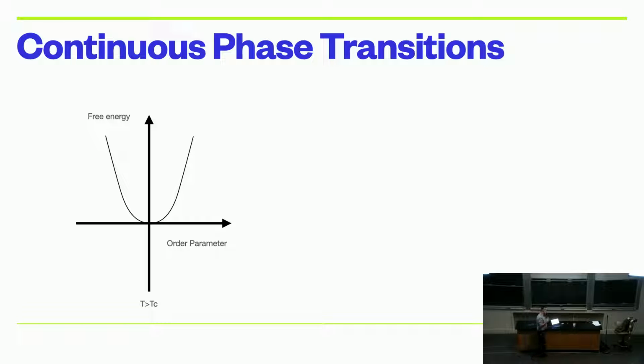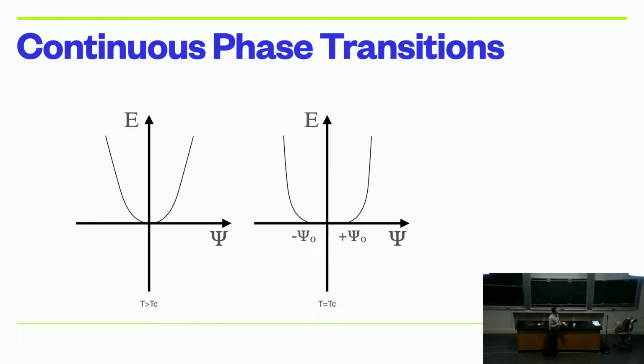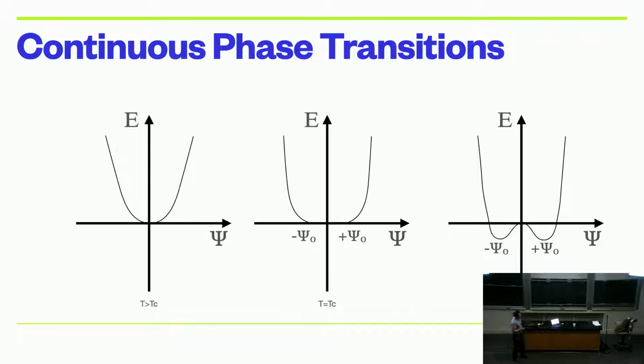Now, as you cool the system, and those other terms in those interactions start to become more dominant, you can describe the free energy in the system in a slightly different way. So let me just give those things symbols. This is my order parameter, this is my energy. And now I'm cooling the system, and I'm seeing how the free energy of the system actually evolves. And I will see that parabola start to flatten out. And then eventually, some finite magnetization, or some finite values of that order parameter start to become favorable. This is a kind of cartoon way of characterizing how a free energy evolves across what's known as a continuous phase transition. And then below that transition temperature, well, now I've got some finite values of the order parameter, which are now at the lowest energy.